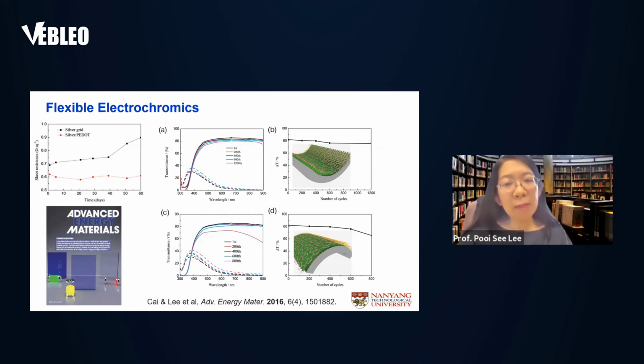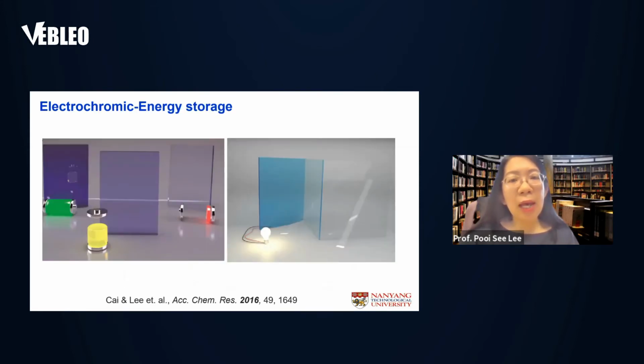More importantly, the mechanical durability is good, whether under concave or convex curvature, it can still maintain a relatively stable modulation in transmittance. And the idea here is that the electrochromic can actually lead to an indicator of energy storage as well, because the amount of charges incurred can be reflected in the different degree of color spectrum.